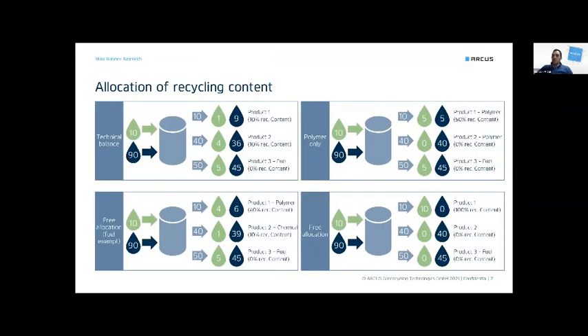So the next step is to discuss in more detail how to implement the mass balance approach for recycled feedstock. We are discussing four possibilities at the European level. The first one is a technical one. You mix 10% of pyrolysis oil with 90% of naphtha and you have a yield distribution. We may assume the same distribution as for naphtha, and therefore 1 of 10 will be in the first monomer product, so we will have 10% of recycling content. The same for a second product going through as a feedstock for polymerization, and then some part of the pyrolysis oil goes to fuel, which cannot be considered recycling at the moment.